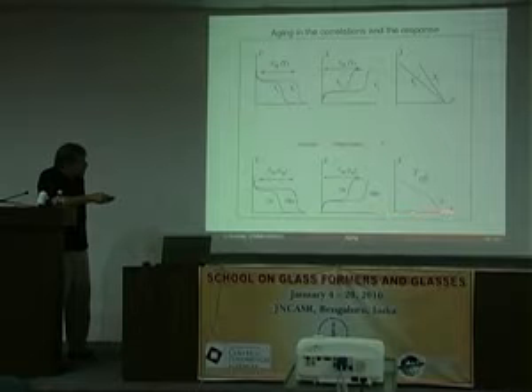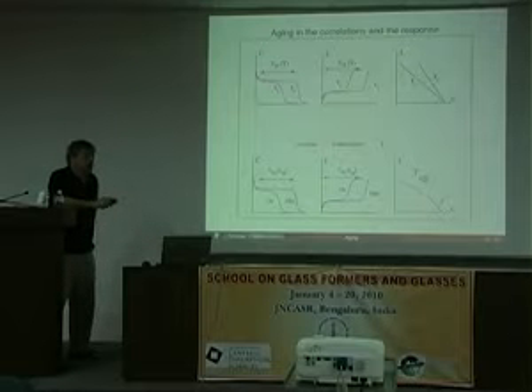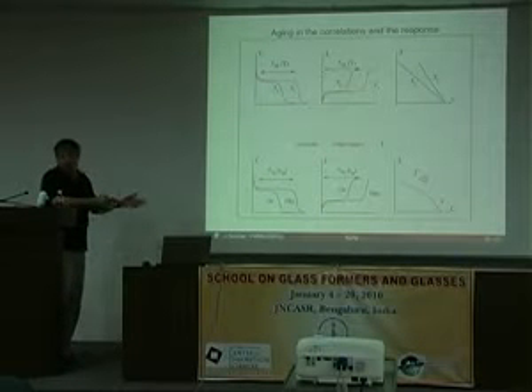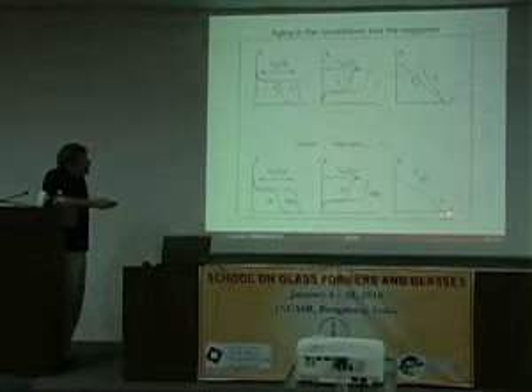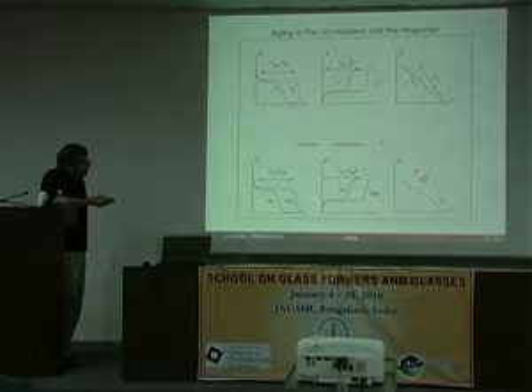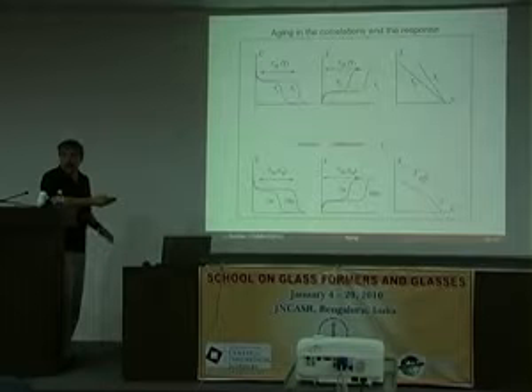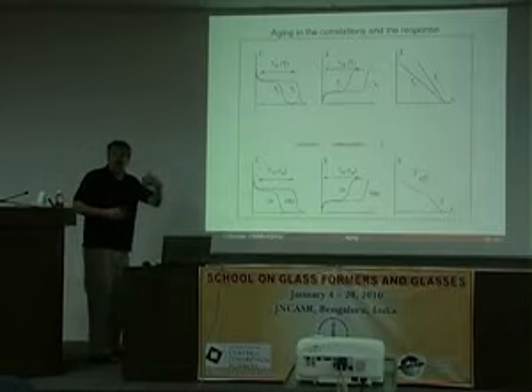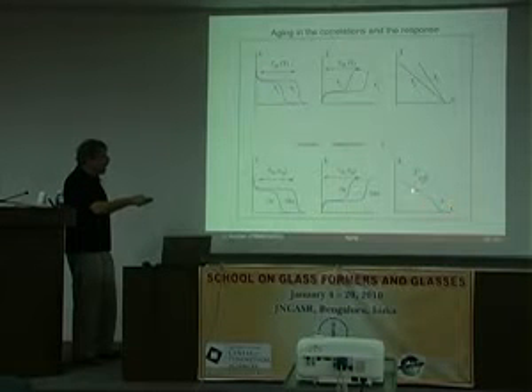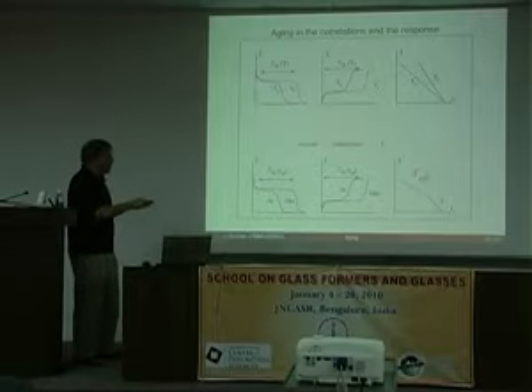And when you did this for the analytic solution, what you find is that, at least for longish times, this curve becomes something like this. All the curves fall into roughly the same. I say roughly because it's an asymptotic statement. It's at long times that they really get on top of one another.